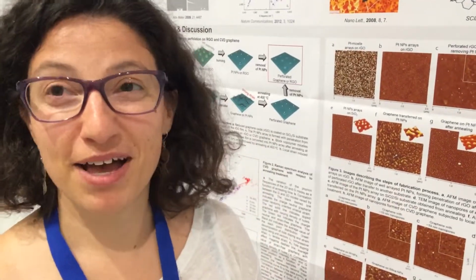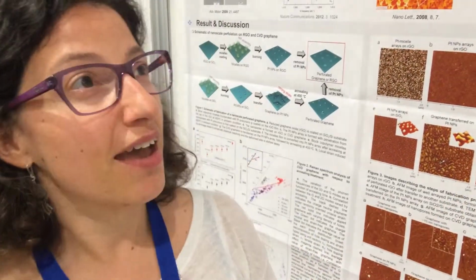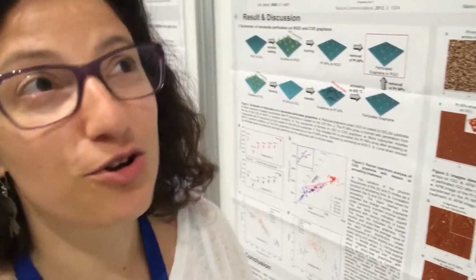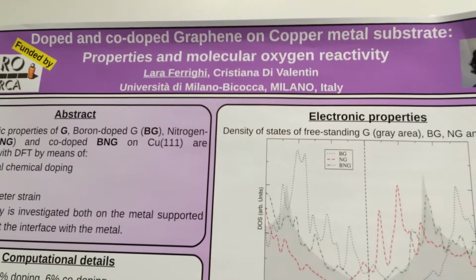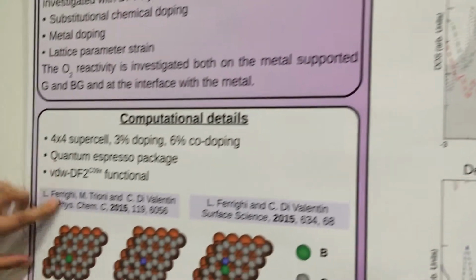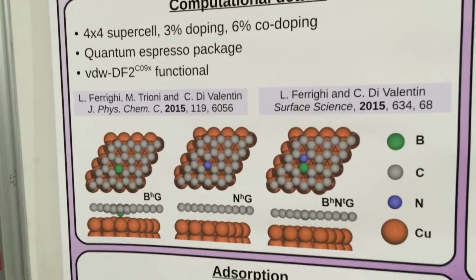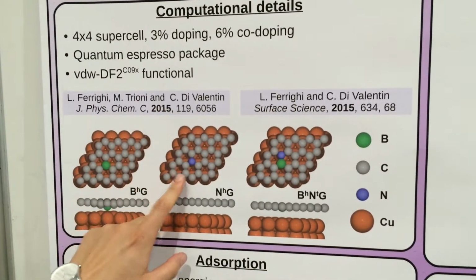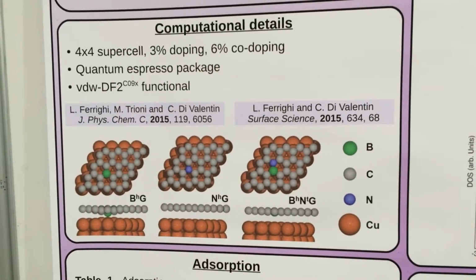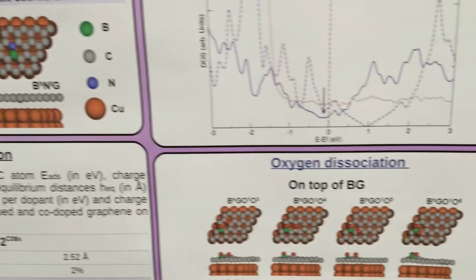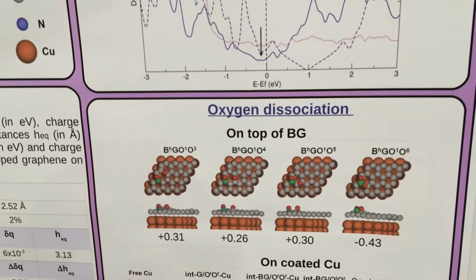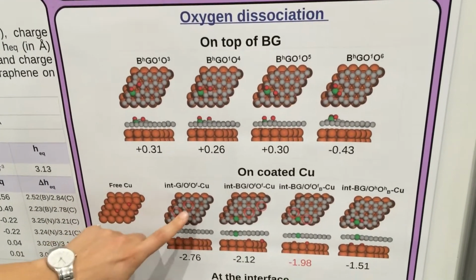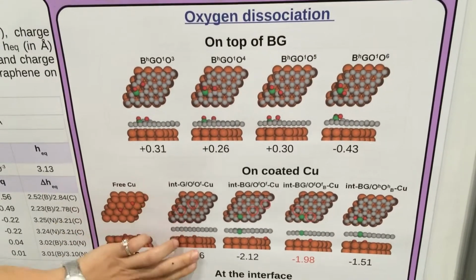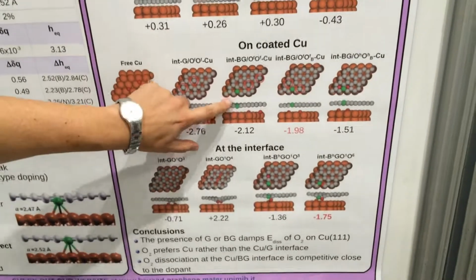Hello, I'm Lara from Milan, University of Milano-Bicocca, and I'll present my poster, Doped and Co-doped graphene on copper metal substrate. We have a study that is divided in two parts. In the first part, we'll just define some doping with boron, nitrogen, and co-doping with boron and nitrogen. And in the second part, we'll look at the oxygen dissociation on metal, copper metal, and on the interface between graphene and the metal, and the interface between boron-doped graphene and the metal substrate.